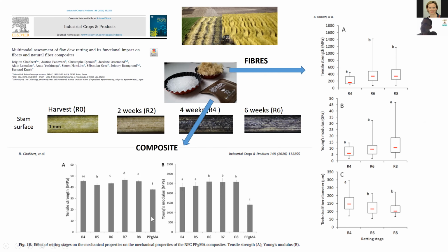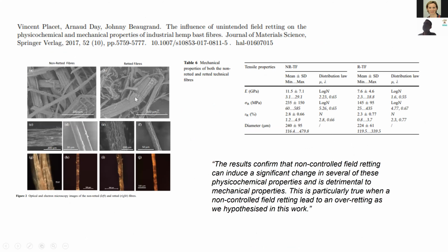This is just a polymeric material, not reinforced by the fiber. But you see that there is an improvement, with some variation according to the retting degree. So even if there are several steps from the retting, recovering of the plant, defiberizing, and then putting this into material, we see some difference. This has also been confirmed by other studies, in other contexts with other materials. And clearly, in this study, it's non-controlled field retting, so they have used plants as they are and managed in a traditional way, I would say.